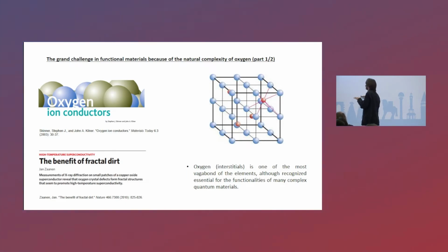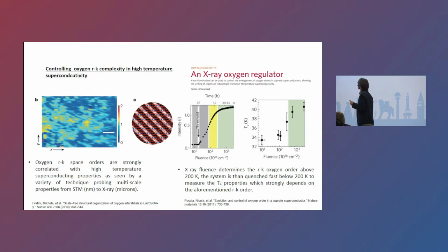There have also been measurements, experiments and theories saying that the ordering of the oxygen in real space, and its K-space ordering, is very important for the properties of the material itself. Lastly, the oxygen interstitial is one of the most vagabond of the elements you can imagine on the periodic table, like hydrogen. Although it is recognized for the functionality of many complex materials, it is very difficult to control. For example, X-ray mapping, as you see in this picture on the left, shows how the K-space ordering of the oxygen interstitials in lanthanum copper oxide varies across a space of several microns. The oxygen K-space orders are strongly correlated with the high-temperature superconducting properties of this system.